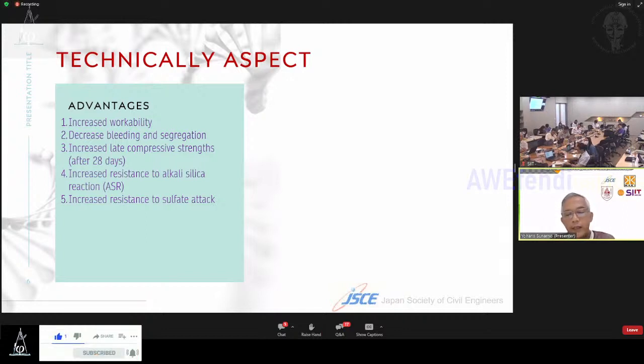So concrete with fly ash can anticipate conditions in a coastal area, where the influence of seawater or sulfate attack can damage concrete performance. Six, less heat generation during hydration. It's very helpful in mass pouring, where usually the thickness of the concrete is quite large, sometimes 1 or 1.5 meters. In this condition, a temperature difference can be a problem, because in concrete, the hydration process can increase the temperature of the concrete.